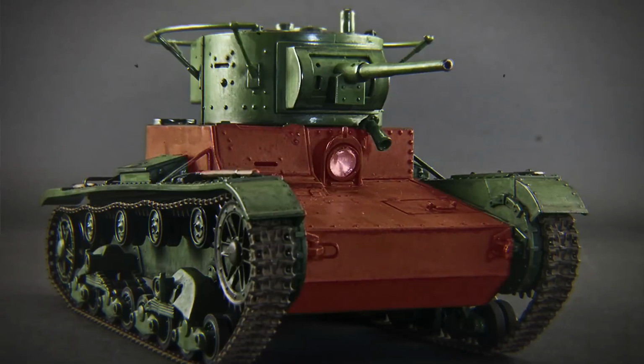But, ultimately, they decided to abandon cemented homogeneous armor in favor of rolled homogeneous armor with high hardness, which could successfully replace it. The Zhdanov factory was the first to switch to it. The T-26 tank received a hull made of this armor. However, to maintain the armor's strength, the sheets had to be made 2-3 mm thicker. As a result, the tank gained an extra 800 kilograms of weight. But under mass production conditions, this was justified.